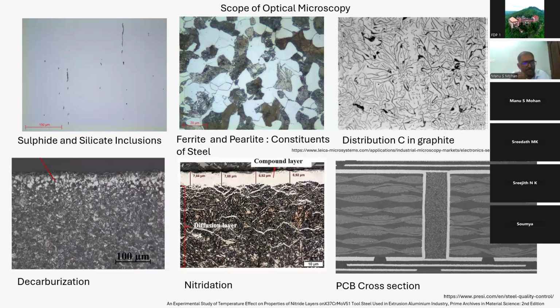So here we see the first optical micrograph. On the left side you can see some marks. Metallurgists or mechanical engineers will know easily, these are the inclusions. Sulfide inclusion is very detrimental to steel because they generally have very low melting points. So when the steel is subjected to any rolling, forming, or other processes, there is a chance for the steel to crack. The crack will nucleate at these inclusions. So these can be characterized by the optical microscope.